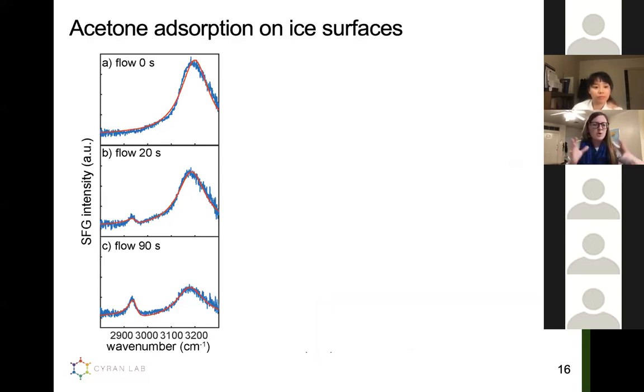But I wanted to give you a broader overview of the results that we got and what information we could get out of this. Here what we're looking at is the SFG spectrum of ice. In A, I have a flow of 0. What this means is I took the ice into the SFG spectrometer and took a spectrum where I'm only flowing nitrogen. I use nitrogen as a carrier gas in order to later vapor deposit the acetone onto the surface.